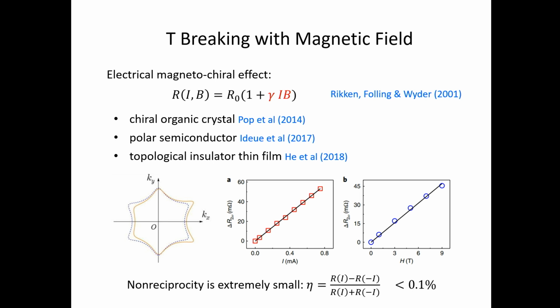The first approach is to break time reversal symmetry by, for example, applying a magnetic field. This has been thought about before, and there are even experiments. In the presence of a magnetic field, a non-reciprocal IV curve is in principle possible, and in fact it has been observed in several materials. For example, you take a topological insulator film, and it has surface states, shown here in the dashed line. When you apply a magnetic field, because the electrons' momentum and spin are locked, the Zeeman energy from the magnetic field distorts the Fermi surface so that E of k and E of minus k are different. The energy momentum relation is no longer symmetric.